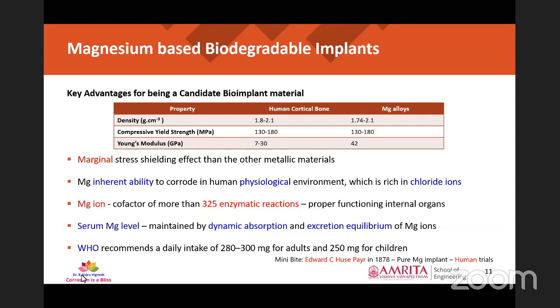By the year 1878, Edward tried out a pure magnesium implant on a bone-fractured human, and the results were astonishing. He found that magnesium is biocompatible, but the problem with magnesium is its high activity that will lead to accumulation of gases near the implant material when it corrodes. That will lead to some sort of lethal phenomenon. So that is one of the major findings of Edward. That led us to research towards biodegradable implants with controlled corrosion kinetics in magnesium alloys.